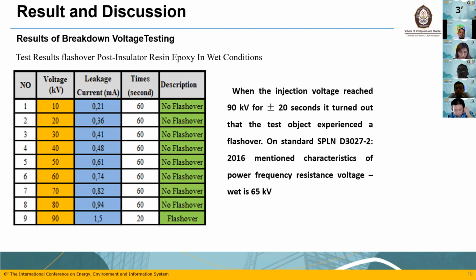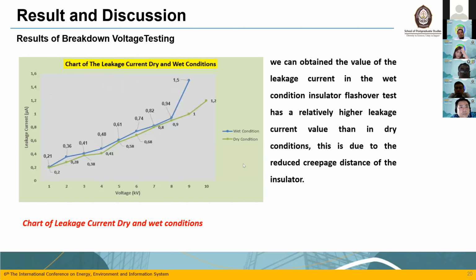Result of breakdown voltage testing in wet condition. When the injection voltage reaches 90 kilovolt for more or less 20 seconds, it turned out that the test object experienced a flashover. The SPLN standard mentions that the characteristic of power frequency withstand voltage or breakdown voltage in wet condition is 65 kilovolt. In this research, the insulator flashover at 90 kV with leakage current and time more or less 20 seconds. This is the graph of the leakage current, dry and wet condition.